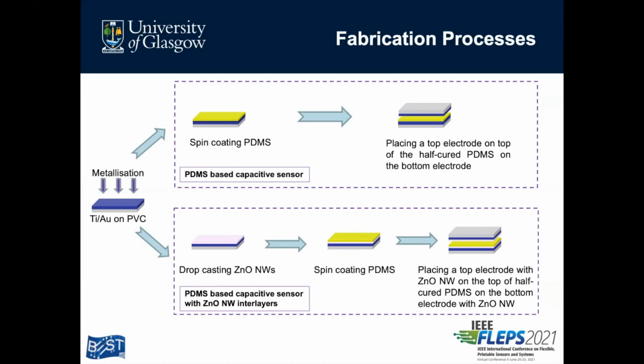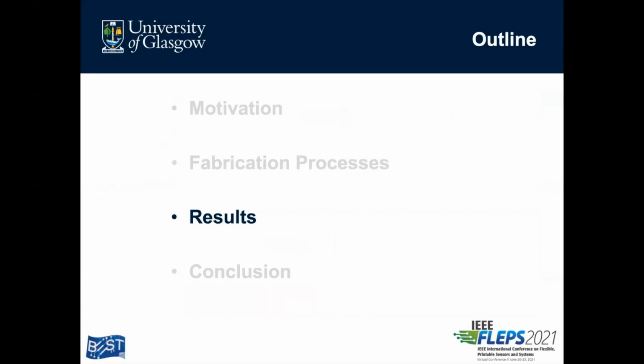For the PDMS-only based sample, we spin-coated PDMS on an electrode, then placed another top electrode over it while the PDMS was still semi-cured to ensure a firm adhesion. For the sample with zinc oxide nanowire interlayers, we firstly drop-casted zinc oxide nanowires on one electrode, then spin-coated PDMS after annealing the zinc oxide nanowires. Then we placed another electrode with drop-casted zinc oxide nanowires on top of the half-cured PDMS. And now I'll be moving on to the experimental results of the two samples regarding their sensing performances.